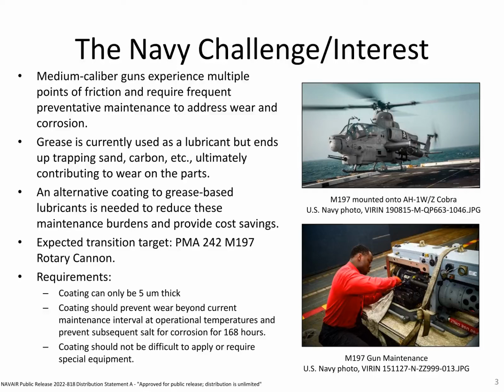So the goal is to replace grease lubricant without altering the part or doing too much to change the nature of the gun. For that reason, the coating can only be 5 microns thick on certain parts of the breech bolt, body, and rotor track of the M197 rotary cannon. Other places can be a little thicker, but 5 microns is the maximum for certain parts on the breech bolt that experience the most wear.